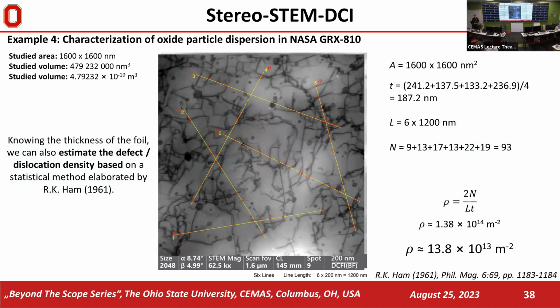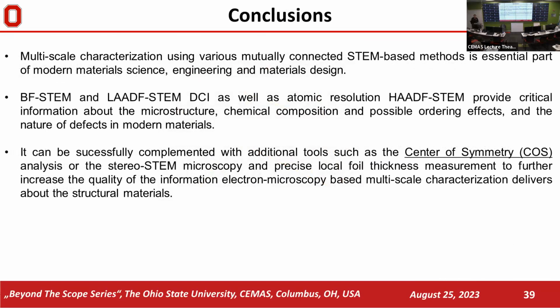So here we are just using a statistical method from 1961, the intersection method, and since we know very precisely the volume and thickness of our area of interest, we can fairly nicely estimate the dislocation or defect density for the area, and we can estimate for the specific area what the Taylor hardening factors are. So this is the level of information we are able to get from that. And this brings me to the conclusions.